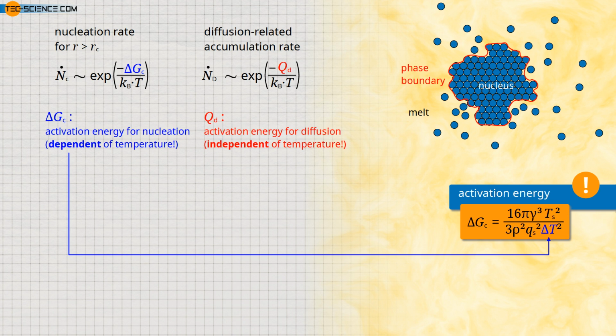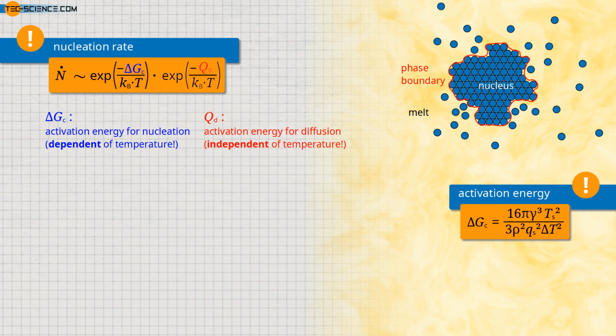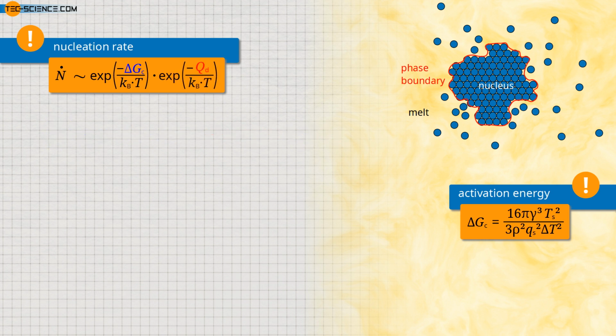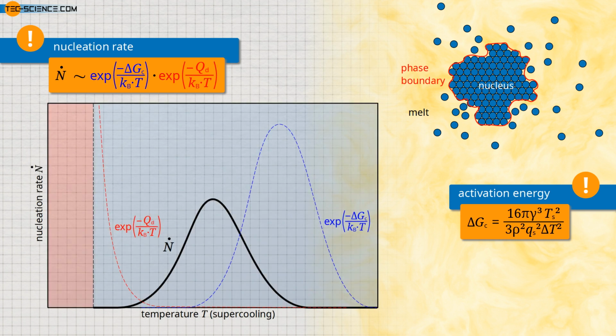Since the total nucleation rate ultimately depends on both of the previously described influences, the overall relationship results from the multiplication of both relationships. Note in this relationship that the activation energy for nucleation depends on supercooling. The diagram shows schematically the influence of supercooling on the nucleation rate according to the derived relationship. It can be seen from the diagram that at low supercooling, the activation energy for nucleation is much greater than the activation energy for diffusion. The formation of nuclei is therefore inhibited by the high energy required for nucleation. Thus, only a few nuclei are formed and consequently a coarse-grained microstructure is obtained.